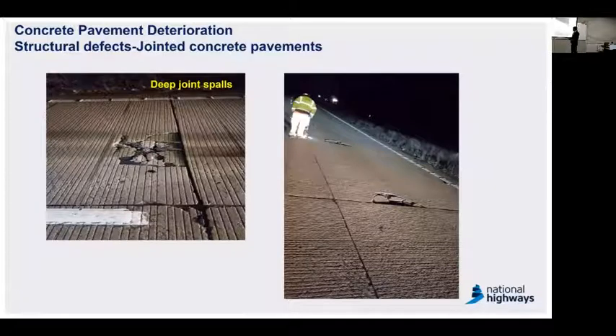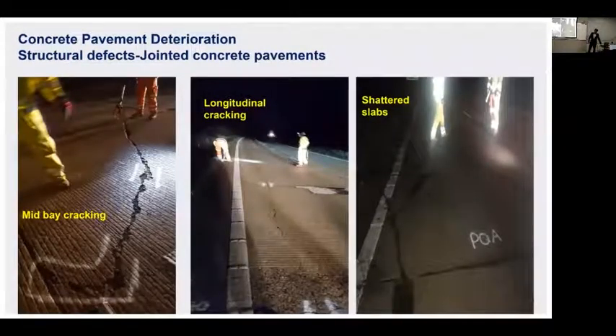On top of that, you have your traffic and environmental conditions, which could lead to these sorts of defects. So the potential causes for the first one are again traffic and the environment, and it's likely to have some loss of localized support. Another issue we need to look at is the potential for drainage issues. No matter how good your concrete pavement is, if you have drainage issues, with water seeping into the concrete pavement or even asphalt, you would still expect poor subgrade conditions that could lead to pavement deterioration eventually.